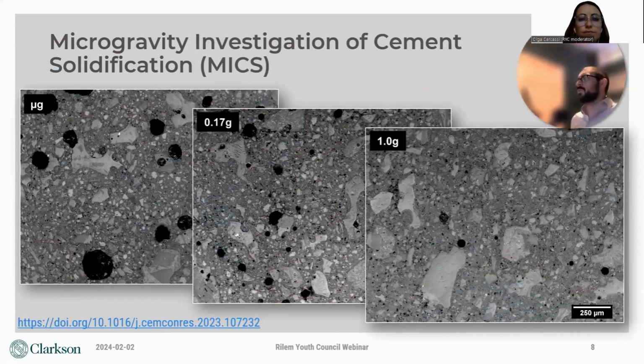And here you see 3 Portland cement samples with lunar simulant aggregates that were hydrated at microgravity, lunar gravity, and Earth gravity. One of the most obvious changes we see is the appearance of coarse air voids in the space-hydrated samples. It turns out that gravity is extremely helpful in consolidating the fresh concrete. We need phenomena like buoyancy to help air bubbles settle out of the fresh concrete, and these effects are diminished at lower gravity. Of course, we know that air voids represent stress concentrators inside the microstructure, and we know that these macroscopic air voids greatly weaken the strength of the material.